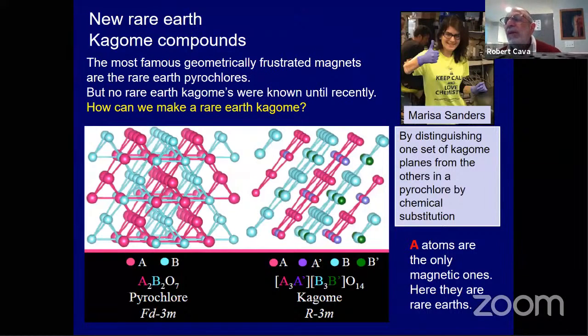So long ago, we figured out that a pyrochlore has two interpenetrating sublattices, and if you consider only the metals, you could put magnetic metals on either one sublattice or the other sublattice. But the whole deal about solid-state chemistry is seeing an overall structure and then trying to get atoms to substitute in a way that gives you something different while maintaining the same basic crystal structure.